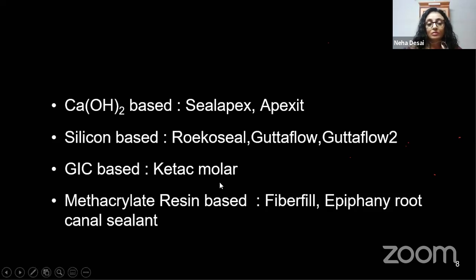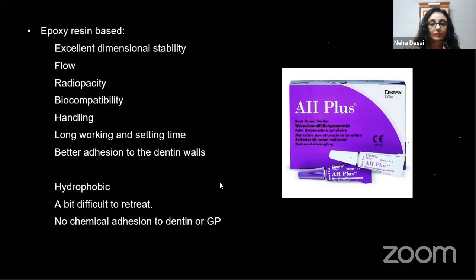Glass ionomer based sealers are not used anymore for their high fluid solubility as well as difficulty in retrieval at the time of retreatment. Methacrylate resin based sealers had issues with shrinkage again, so they are also not used anymore. The epoxy resin based sealers are the most popular right now for their excellent dimensional stability, the flowability, radio opacity, biocompatibility, handling characteristics, long working and setting time, and better adhesion to the dentinal walls.